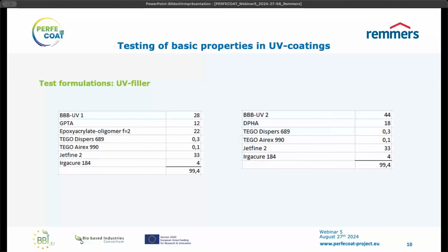Here you see 2 UV filler formulations based on the different bio-based binders. In these real filler formulations, of course, it's not only binder and monomer anymore. Here we have some inorganic filler, the Jet Fine 2, which is a talcum grade, and makes up 1/3 of the whole recipe. And then you see here for the bio-based binder number 1, we have 28%. Which means on the organic part of the formulation, we already have a share of 42%.